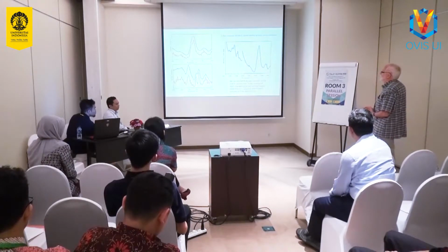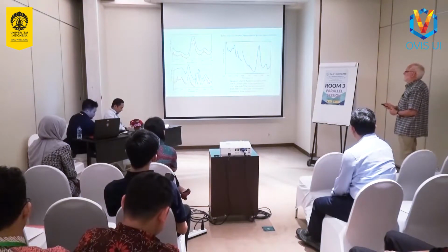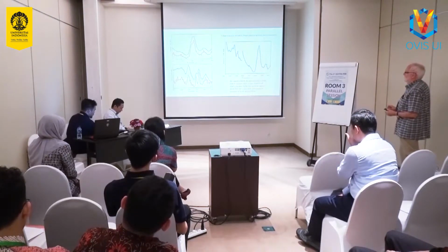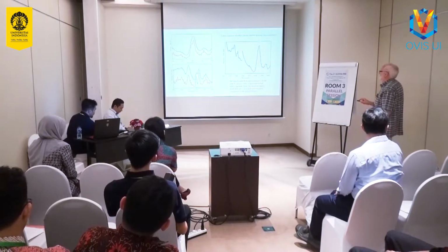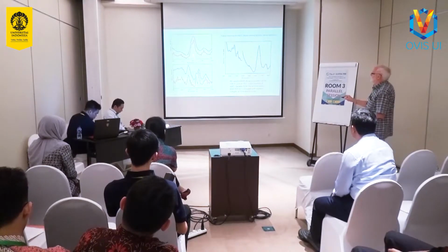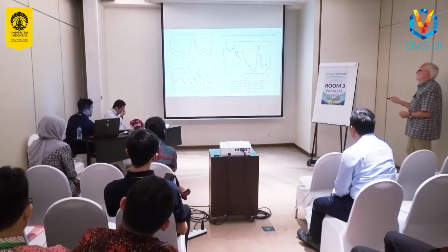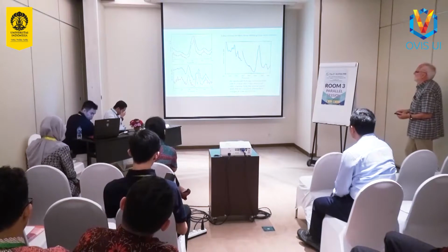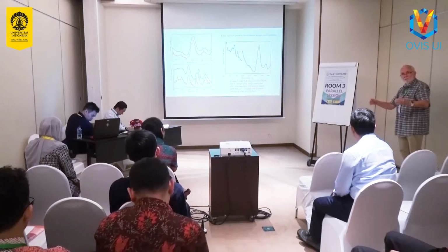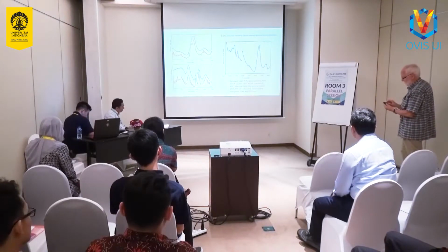If we go to 400 degrees, the catalyst continues to work at 400 degrees. It actually has a somewhat different composition. If we look at the spectrum at 400 degrees, we see fewer methyl groups and more aromatic. If you look at the profile of this band compared with over here at 350 degrees, and if you look at these bands relative to these, we can see some differences, which suggest that at 400 degrees we're making hydrocarbons which are less methylated and more polycyclic aromatics. Again, the catalyst is still active, so this is a live catalyst, not a dead one.